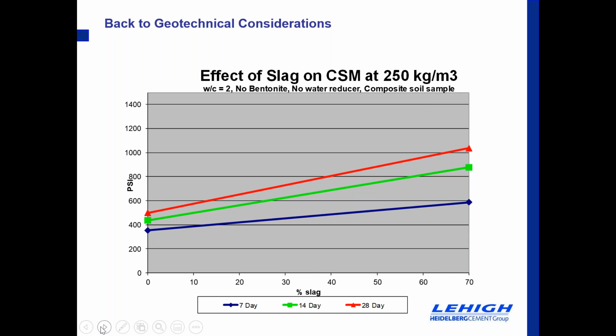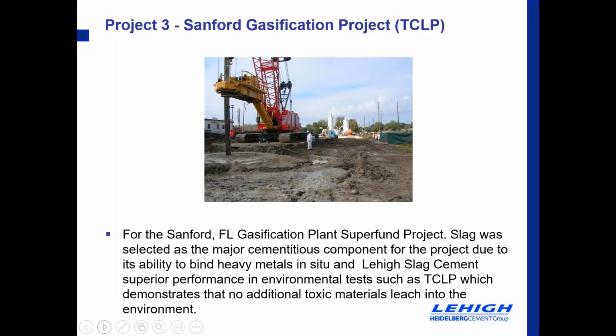So 7-day, 14 and 28 days, we were targeting, I believe, 800 PSI, and we were well within that target range. So the decision was simply the lower total cementitious, the 250 kilograms per cubic meter, and 70% slag. Next, please.